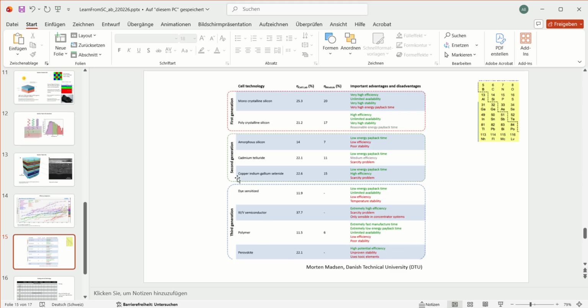And the third generation of solar cells, some of them based on materials that are quite cheap actually, like polymers. But the question is a bit their stability, because if you take the sunlight with its ultraviolet, hard ultraviolet, then they could degrade quite a bit, and also water can degrade them. So they're still quite experimental. Some can be very efficient, like the 3-5 semiconductors.